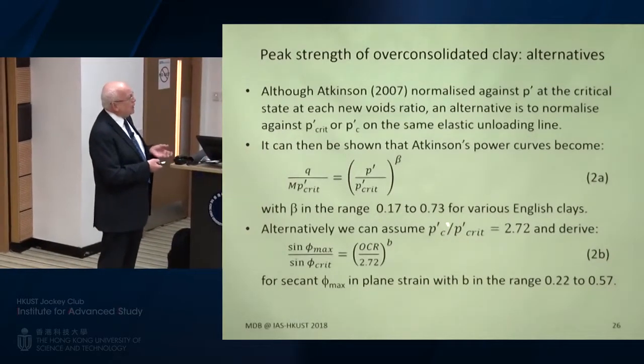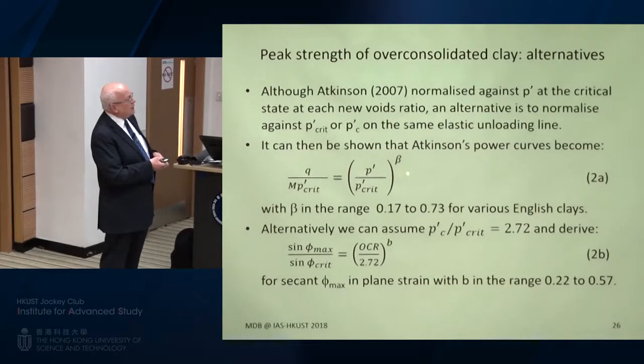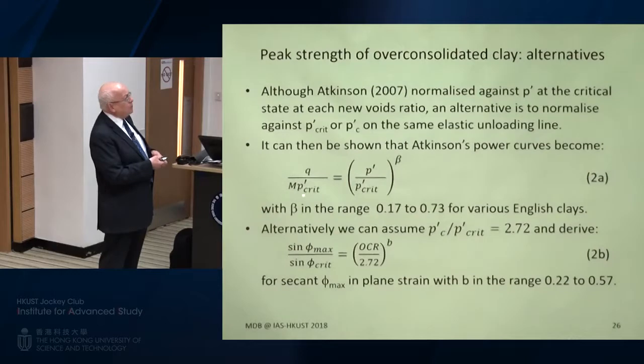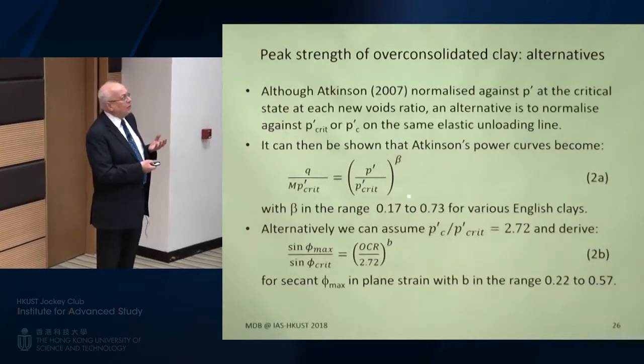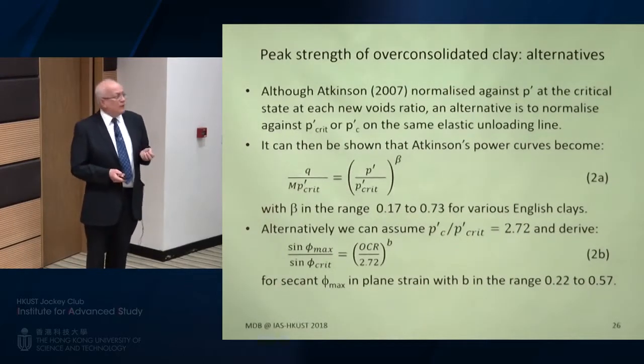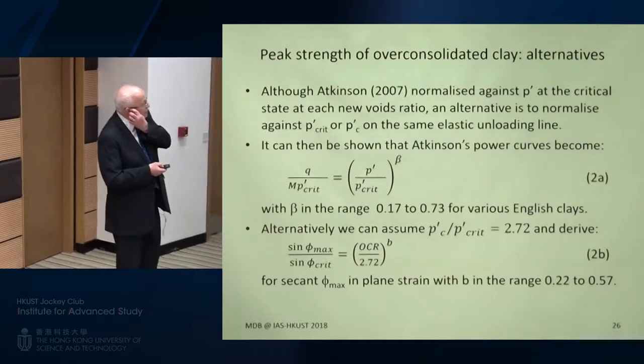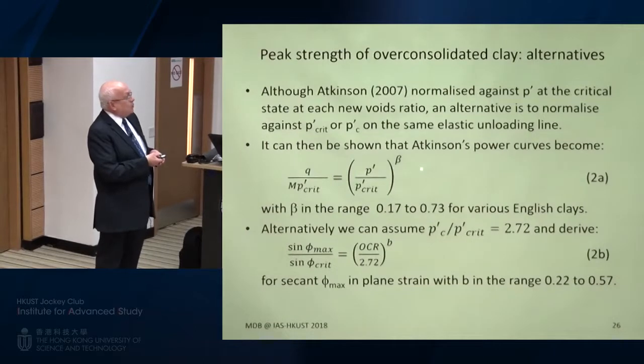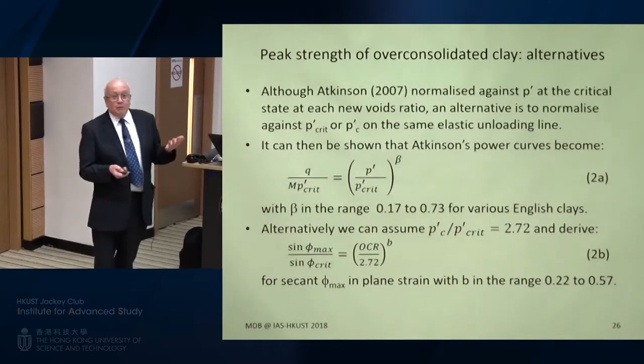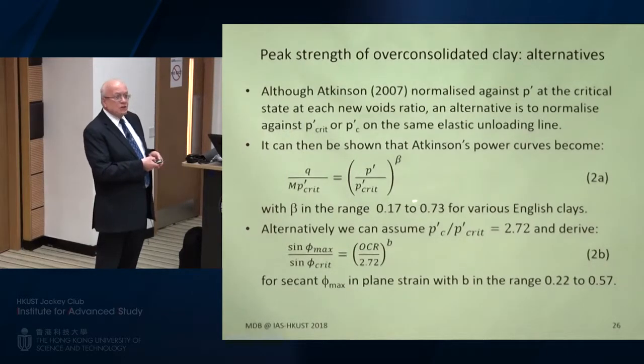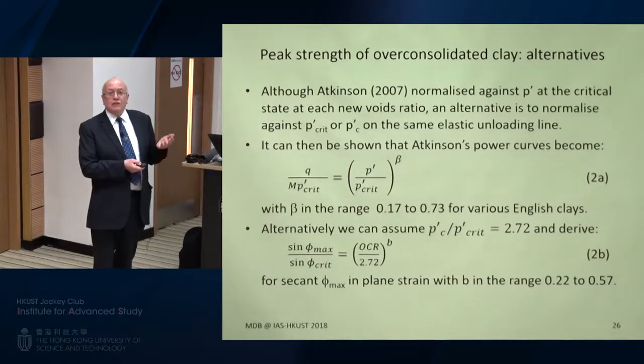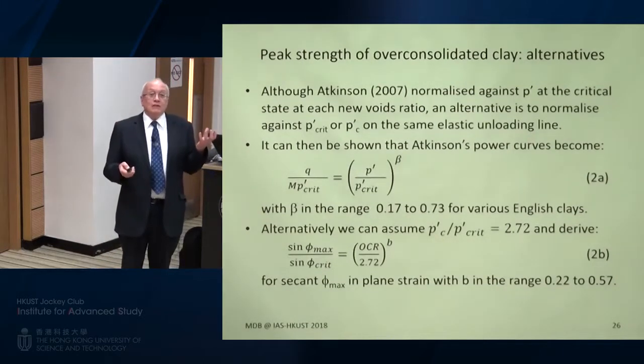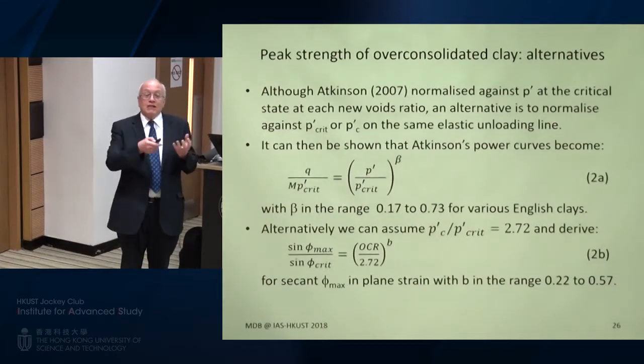And so it shouldn't be a surprise that the propensity of different clays to damage in different respects and therefore give you peak strength curves, power curves with different exponents might well be perfectly sensible. I mean, if beta equals 1, there's no peak at all. If beta was 0, it's a rectangle. So as you over-consolidate, there's no drop-off in the strength. It remembers, as it were, that you made a dry stone wall out of it at high stress. But because it's now a dry stone wall, it's completely stable when you reduce the stresses.